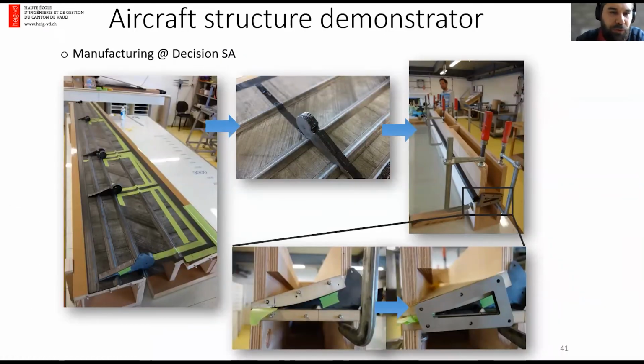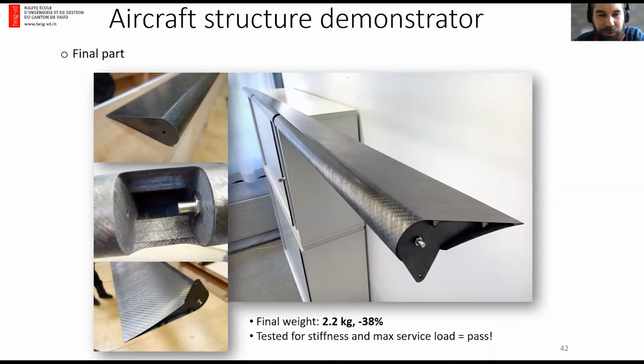And one of the tricks used to simplify the manufacturing was to use the flexibility of the thin plies. As the skin thickness here is very thin, in some areas it's less than 1 millimeter thick. We actually cured the outer skin of the aileron on a flat mold, and then we formed it elastically after curing on the ribs, and we use adhesive bonding and some clamps to close the aileron. And this is very interesting because it shows that you can actually use the elastic flexibility of the ply to form an aileron after it has been cured. And we did check in terms of mechanical testing, and it passed all the criteria. So it's clearly a pass. So in the end, we saved 38% weight.